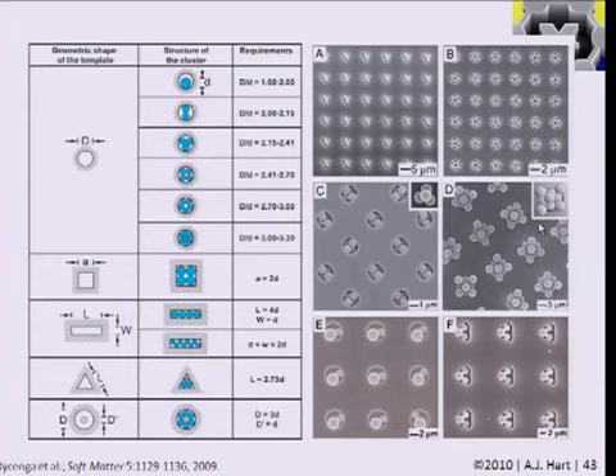And you can imagine the ability to execute this process depends very much on the precision and dimensional limits of the lithography process. So if, for example, you wanted to pack particles that had a 500 nanometer diameter and wanted to discriminate between the assembly of dimers and trimers, then this nominal width would be 2 times 500 nanometers, so 1 micron. That would mean that you'd need to control the lithography process within the hundreds of nanometers range. So this is something that is really at the limits of optical lithography to even create structures that can pack small numbers of particles that are really in the micron range.